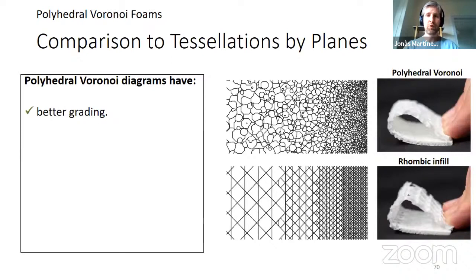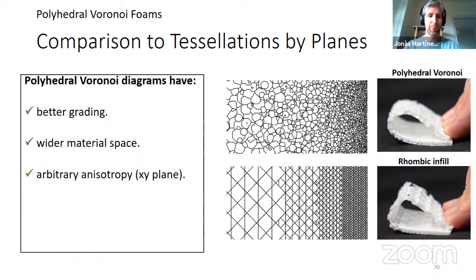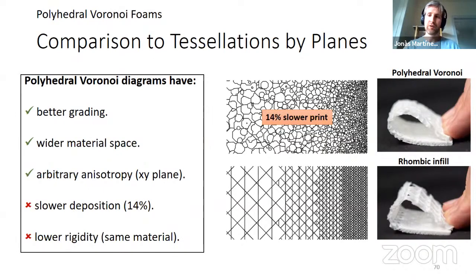And finally, compared to the most classical tessellations by planes, what is nice about this kind of stochastic structures is that they allow for very continuous gradation. Since you don't have this underlying grid, you can do more smooth transitions. And you have here a visual representation. On the contrary, they print slower because of the stochastic geometry. And also, if you want to achieve extreme rigidity, usually it's a better option to use non-stochastic, but regular structures that are designed to be very stiff.